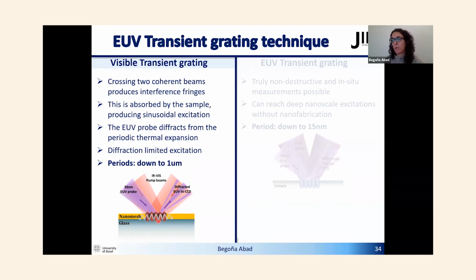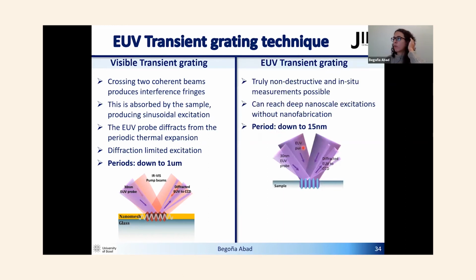This period depends on both the angle and the wavelength. So if we are able to cross two beams with dramatically reduced wavelengths, we will be able to explore really, really small periods. This is what we wanted to do in this experiment, to have truly non-destructive and in situ measurements, because in this case, we wouldn't need the fabrication of the metal nanolines, and we could reach periods down to 15 nanometers.